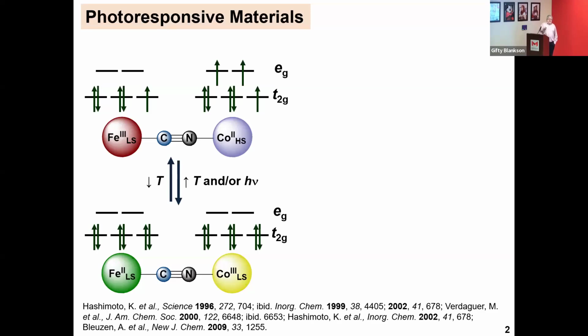Likewise, you also have cobalt-3 low spin, 6 electrons total. They're also spin paired, diamagnetic. When you increase the temperature or shine light on it, you affect a single electron transfer between the iron-2 to generate an iron-3. So you remove a t2g electron and you transfer it to the cobalt-3.